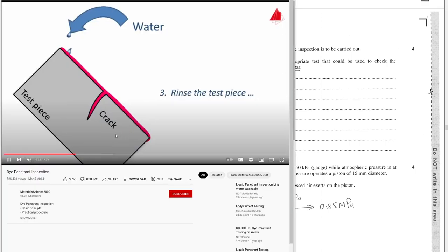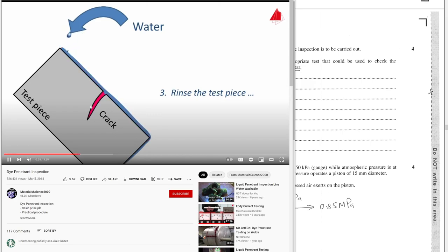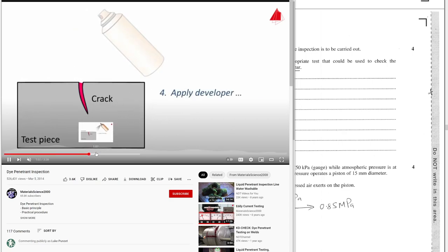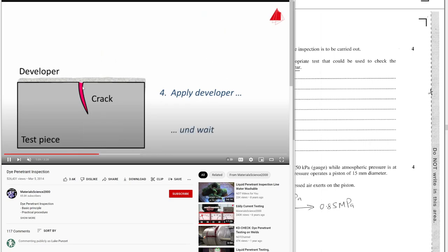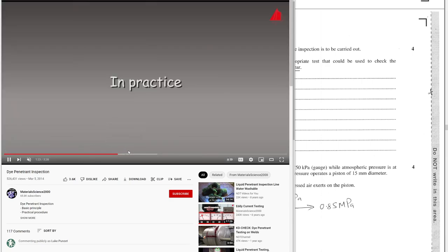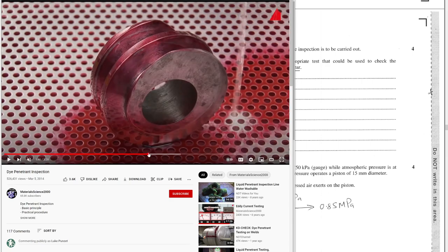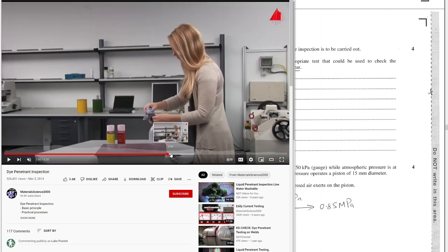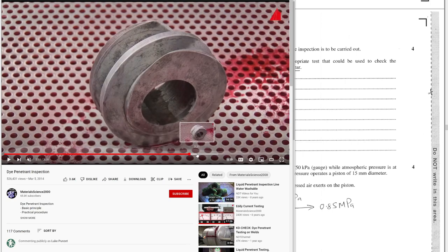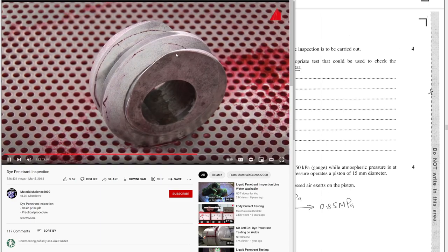So the last one I'll show you is the dye penetration test, which I think is pretty good. This is the pink dye. So what we do is we spray the stuff with pink stuff, then we wash it away. Then we go over it with, because otherwise it'd just be pink, right? Then we go over with the developer, we spray that developer on, and then the pink stuff, the capillary action pulls the pink out into the developer, and you can then see the crack is like 10 times bigger. Crazy, right? So here she is, she's made everything pink, washed it off, spraying on the developer. Okay, spraying on the white developer, and then look at them cracks, right?